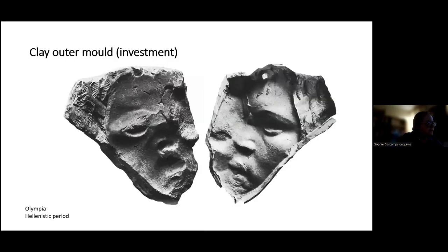Only this example to show you a clay outer mold, the fineness of the first layer of the casting mold to preserve the surface of the wax model. So it was a state of liquid slip to follow the details and preserve the details made in wax. And you have on the left the fragment with the negative impression of a young Black head, and on the right, the positive, the modern positive.